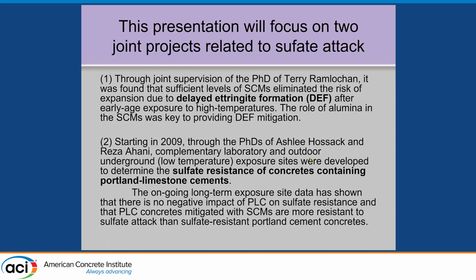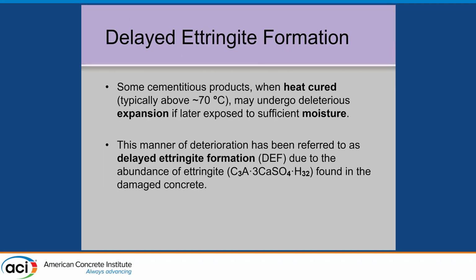And then in 2009, we had 2 separate PhDs, but jointly funded by the Cement Association of Canada to look at the sulfate resistance of these Portland-Limestone cements because it was a concern. And the results have shown that there isn't a concern, and so they're now allowed. That's the quick and dirty summary.